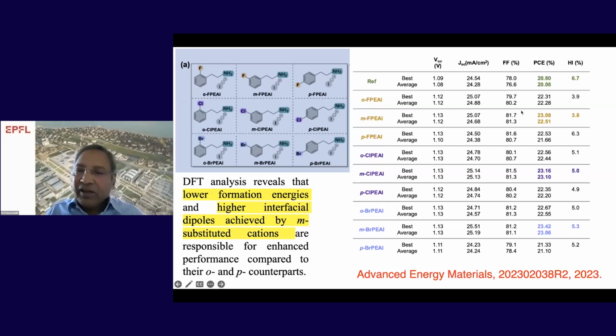Now look at the efficiency data of the reference sample without any two-dimensional perovskite on top of three-dimensional perovskite. The efficiency is around 20%. Now, if we put the ortho-fluoro substituted one, that's the top left corner cation, you can see the efficiency increased from 20 to 22.31%. And if you take the meta cation, which is the meta-fluoro substituted phenylethylamine, the efficiency increased to 23%. And similarly, the para one is again lower, that's 22%. But if you compare fluoride versus chloride, the chloride is almost the same or slightly enhanced when compared to the fluoride, and the bromide is also similar to the chloride, slightly improved.